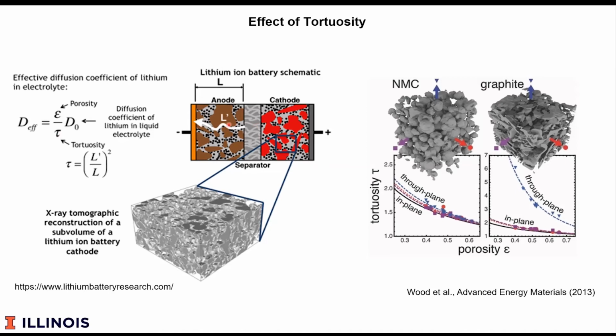And that's just shown here: the tortuosity in the anode and the cathode. The anode, which is made of graphite sheets, the in-plane or the through-plane tortuosity blows up when the porosity goes below 30 to 40%. And so that really limits the volume fraction of graphite that one can use. And even in something that's a roughly spherical particle, by the time the porosity gets under 20 to 30%, it also becomes a significant issue. And so that's one of the advantages of deterministically controlling the electrode structure.